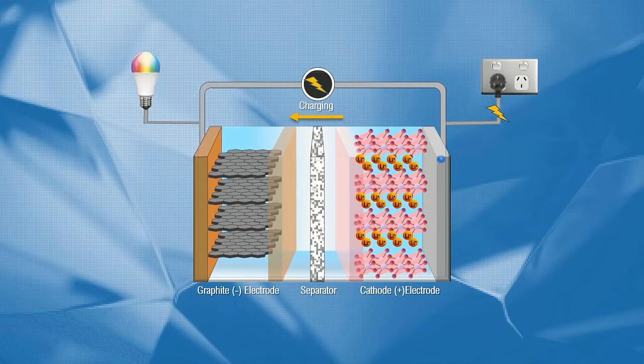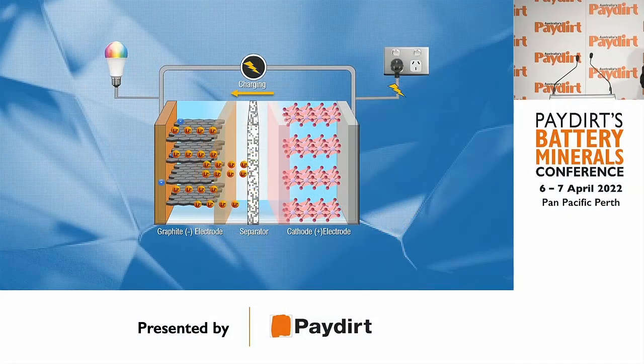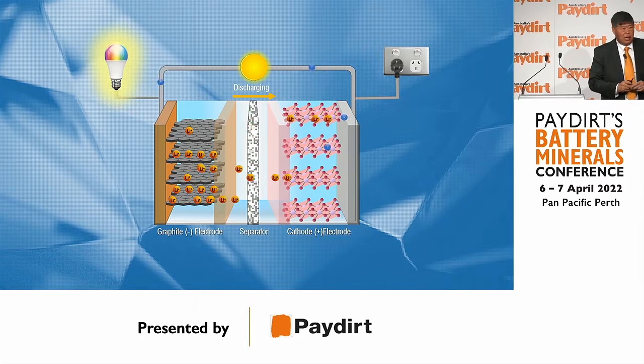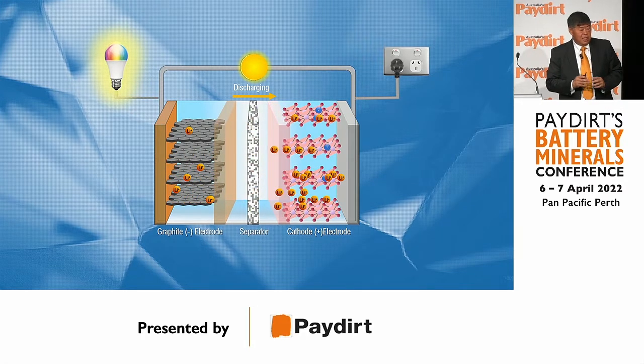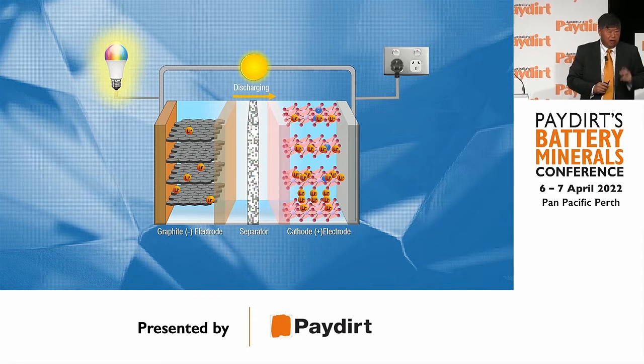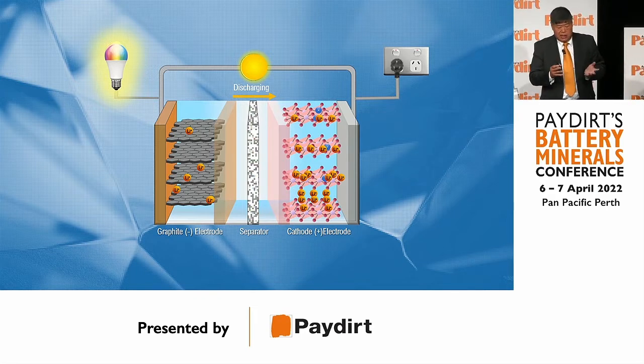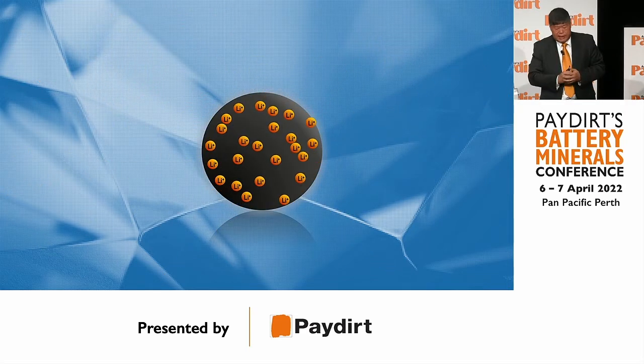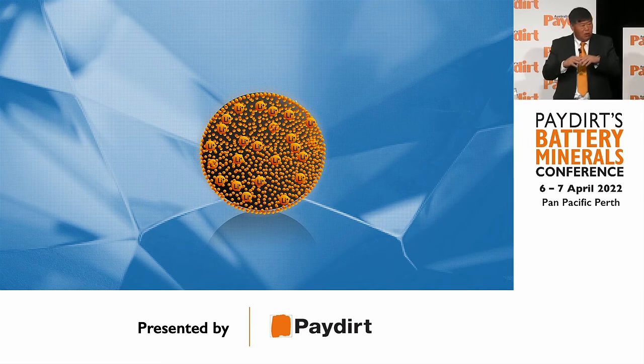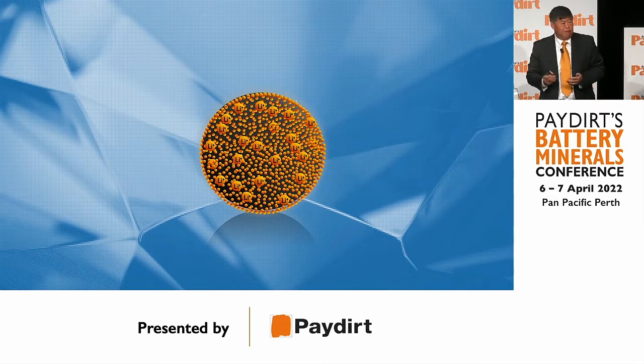Good morning, everyone. Just to give you a background of how a lithium battery operates, as you charge a battery, all the lithium ions go from the cathode to the anode, which you know. And when you discharge a battery, all the lithium ions go back from the anode to the cathode. What a lot of people don't realize is that about 8% or 10% of the lithium stays on the anode side on the first charge, and essentially the lithium becomes inactive to the battery. So what happens? It forms an SEI layer on the first charge, and all the lithium ions that form in this SEI layer don't play any part in the future performance of the battery. This is called the first cycle loss capacity.